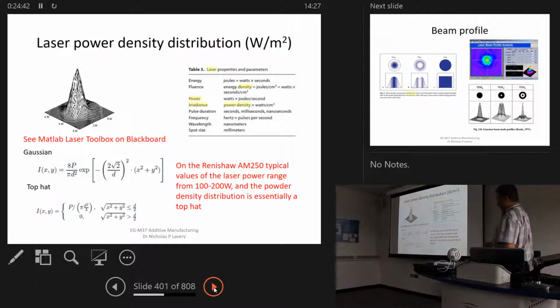Now, in terms of the beam profile, this is something that we have to calibrate on a regular basis on the machines. They can go out of calibration after a while. You need to reset and make sure that your laser is coming down. Ideally, you want a nice round spot size, but we know already that there's variation because of the way the laser comes down and is mainly angled with the focusing into the middle of the plate. By the time you move out to the extreme corners of the build plate, you're starting to get more elliptical shape